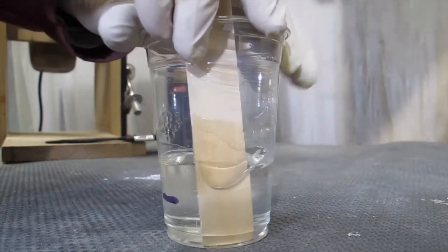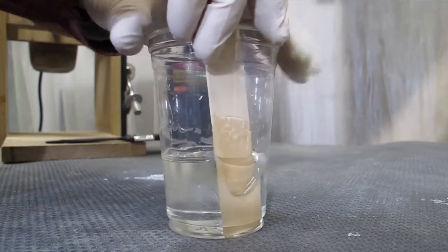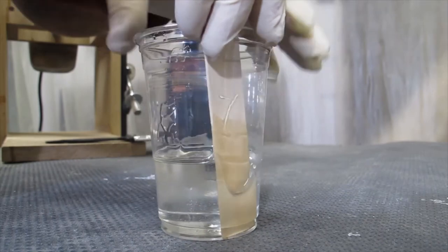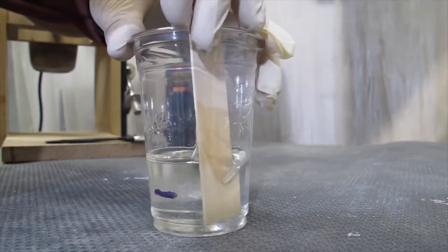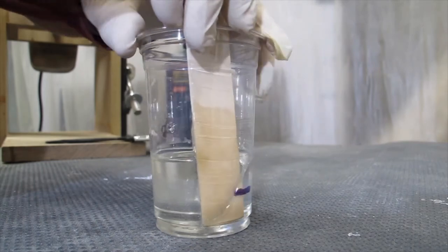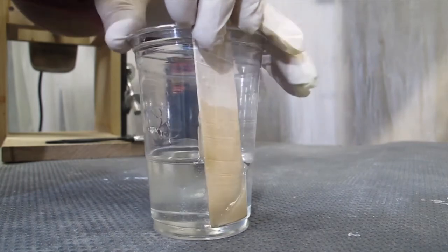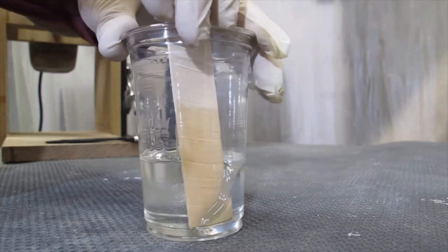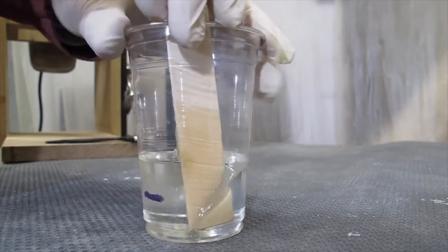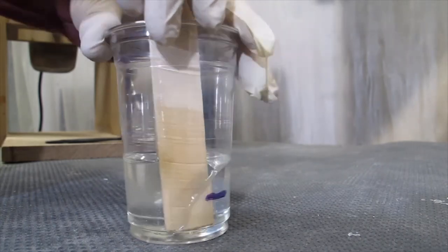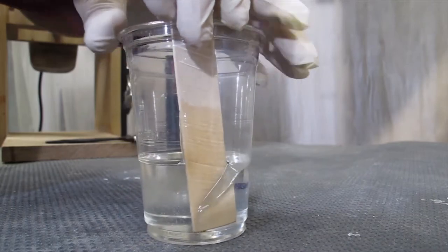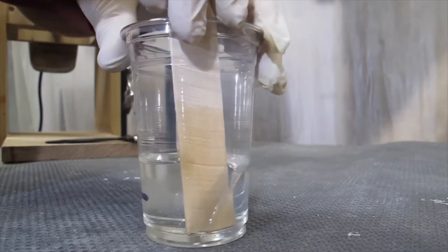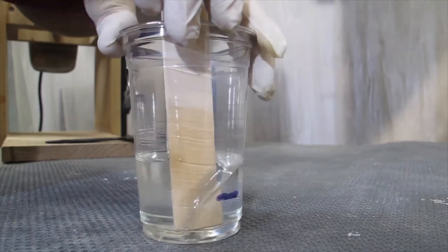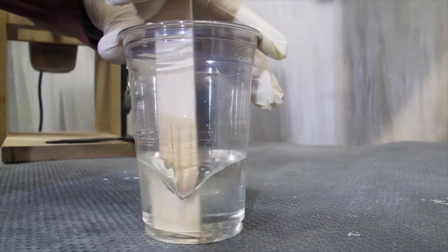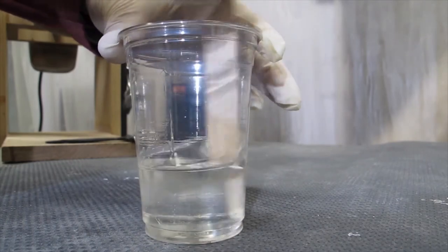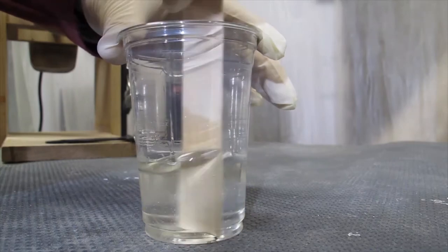When you scrape the edge of your cup, sometimes there's a ridge in the bottom of the cup, and I have to raise my stir stick above that ridge so that I get good contact with the edge of the glass when I am stirring it. Of all the resin I've ever mixed, doing it this way, I've never had a failure. It's always cured.